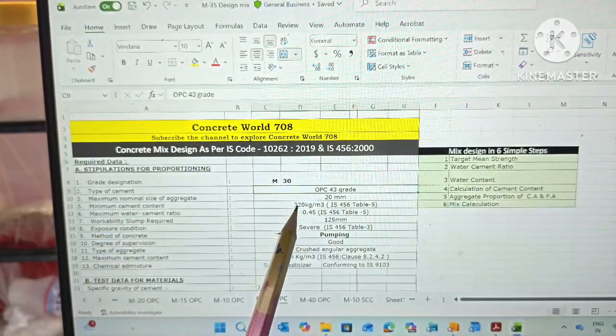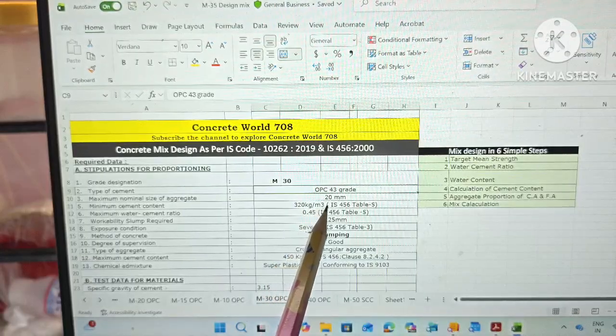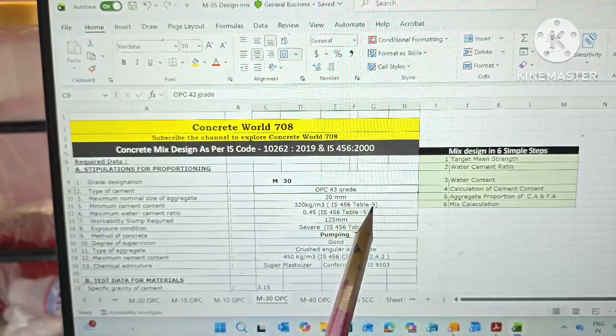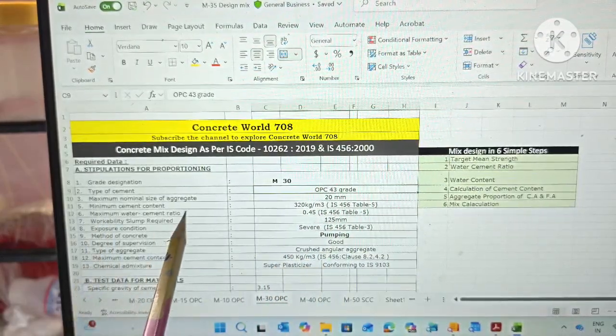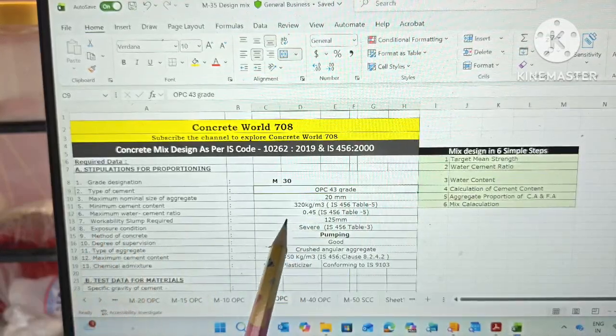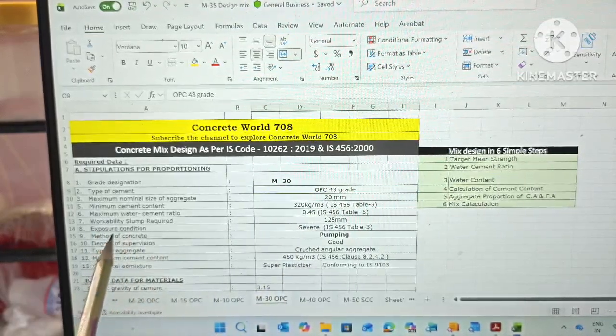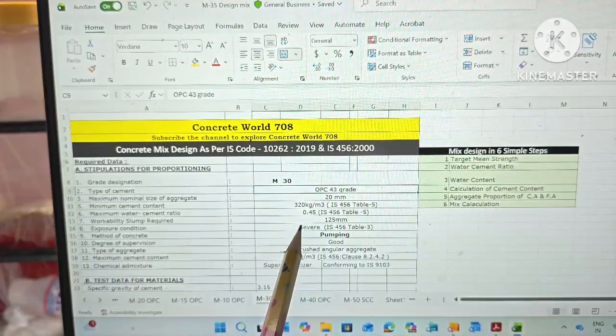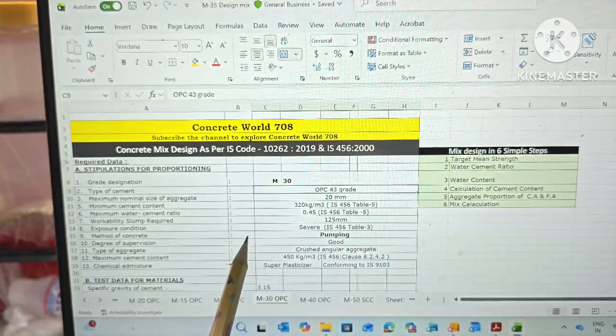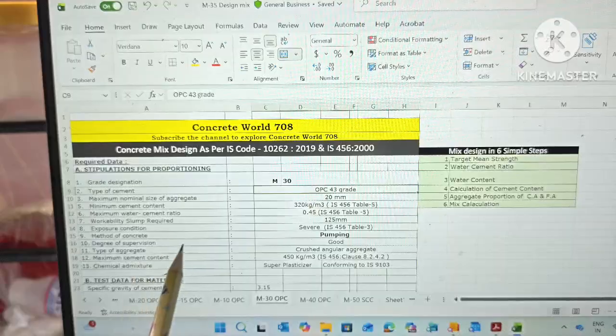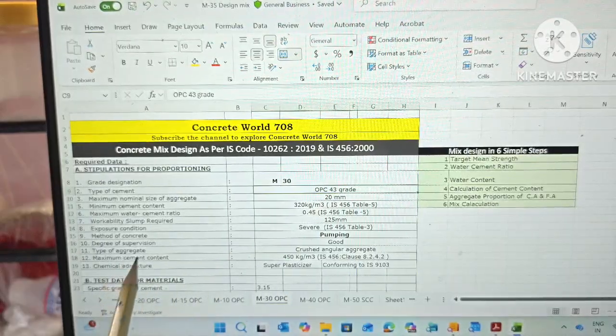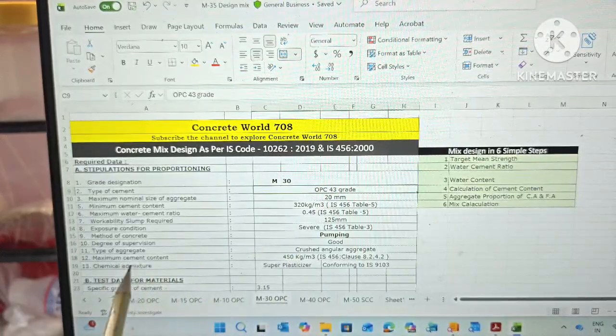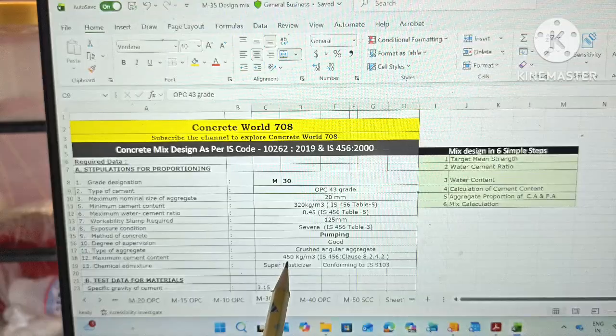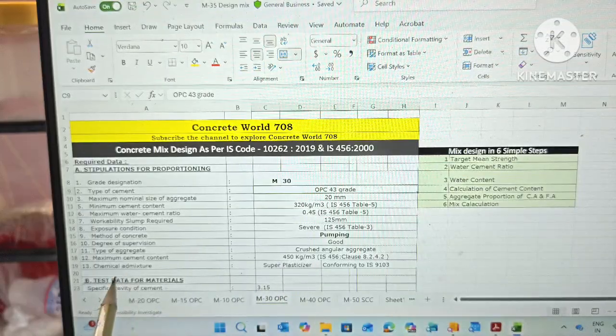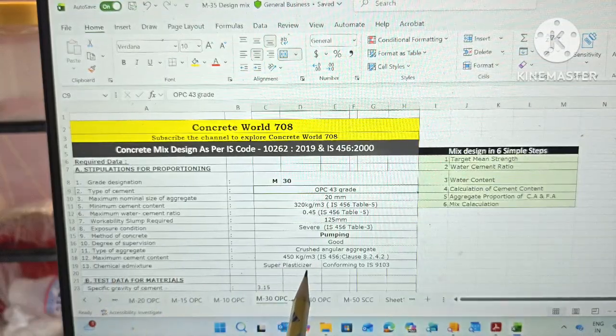Minimum cement content 320 kg per meter cube as per IS 456 table number 5. Maximum water cement ratio 0.45. Workability slump required 125 mm. Exposure condition हमारी है severe. Method of concrete है pumping. Degree of supervision good. Type of aggregate crushed angular. Maximum cement content 450 kg per meter cube. एंड केमिकल एडमिक्सचर यूज्ड इज सुपर प्लास्टिसाइजर.